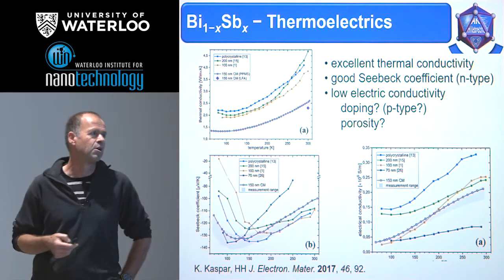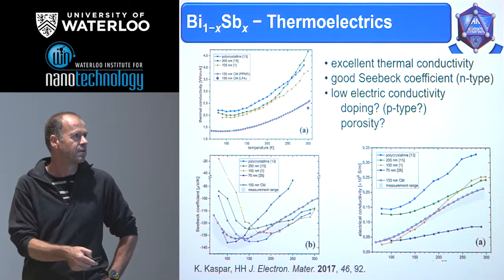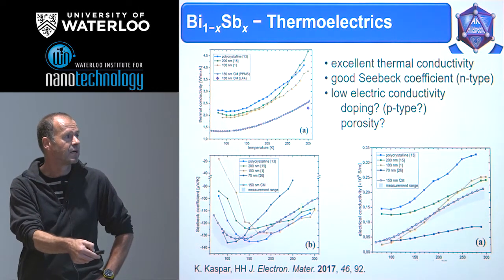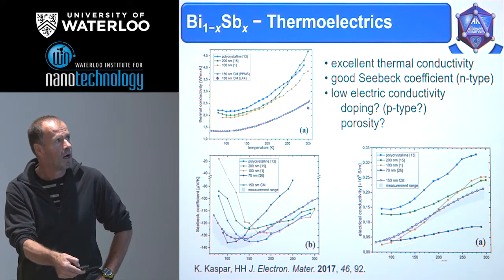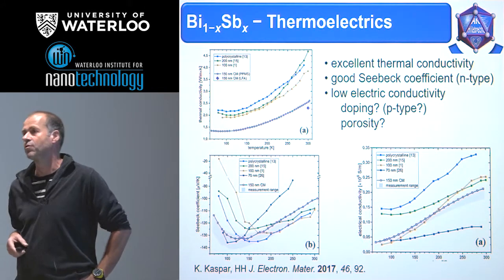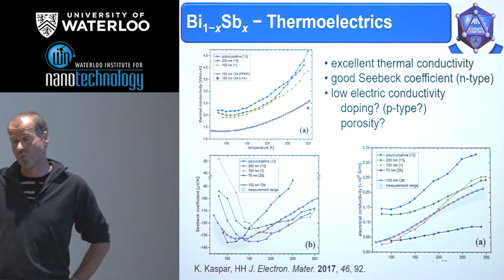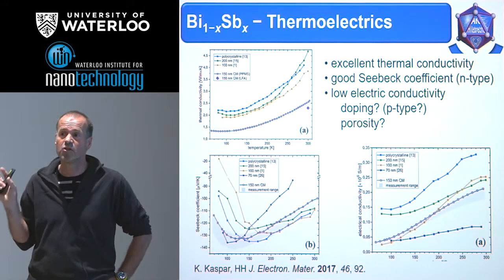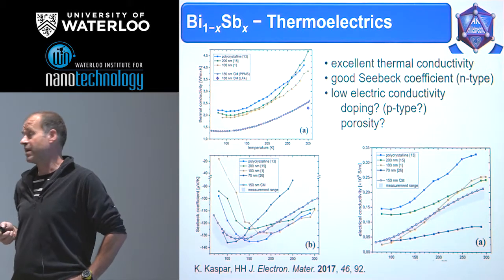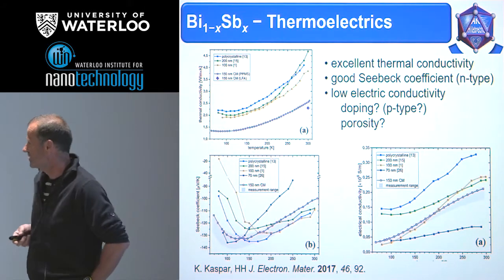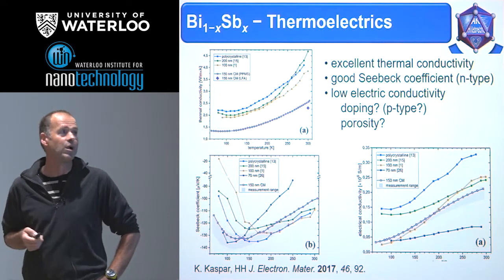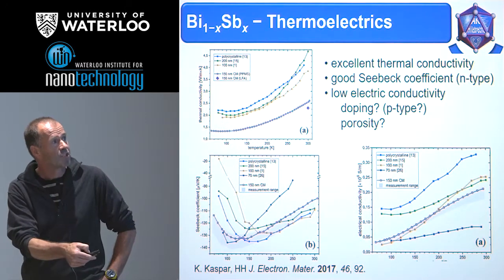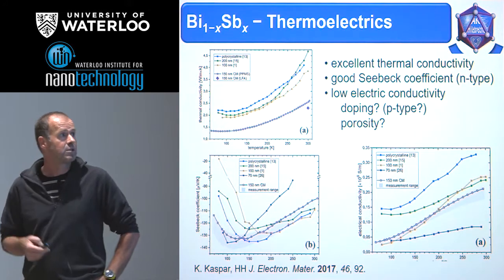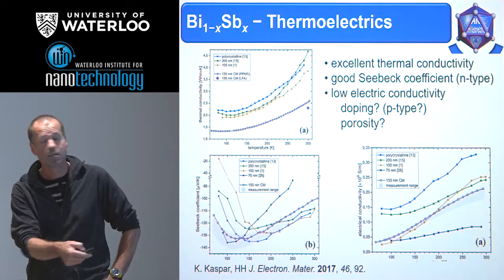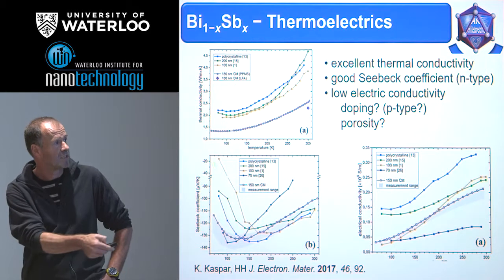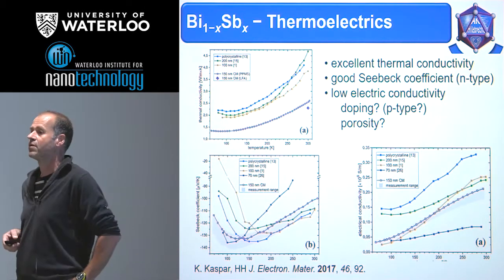We have a quite normal Seebeck coefficient, and we have a quite low electric conductivity. So this is a point where we should work on our process, and it is the weak point that we didn't get better values. I guess Holger was saying, yes, there's still some work to do. Well, we are doing that. One problem is the doping. Usually most of the material is an N-type material by itself, and that's what you see from the sign of the Seebeck value, that we have an N-type.